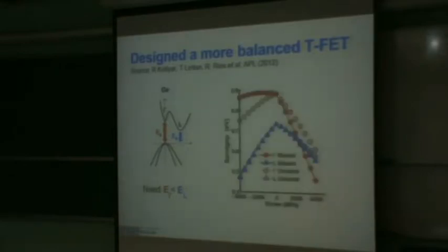So we did that by modulating it with stress. Let me explain what I'm showing here. In blue, this is the band gap in the L valley. The red curves are the band gap in the gamma valley for two different kinds of strain. We're looking for the condition where the red curve becomes smaller than the L valley. One kind of stress is tensile stress, where we're pulling the atoms a little further apart in the lattice, and the other is compressive stress, where we're pushing the atoms closer together. It turns out we find the indirect to direct transition at about 2,500 megapascals on the germanium. Okay, that's quite a healthy bit of stress.